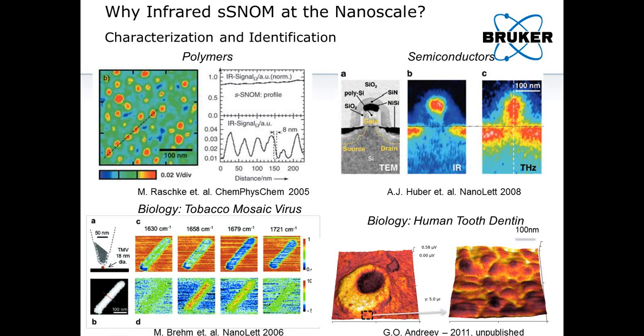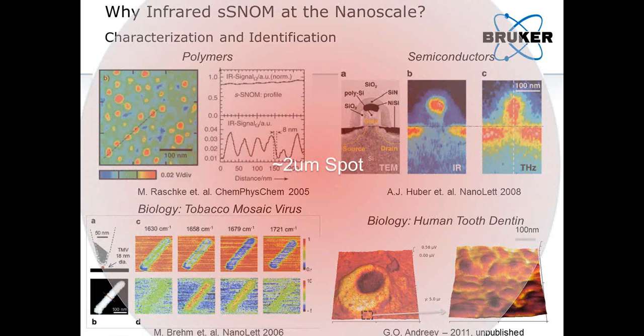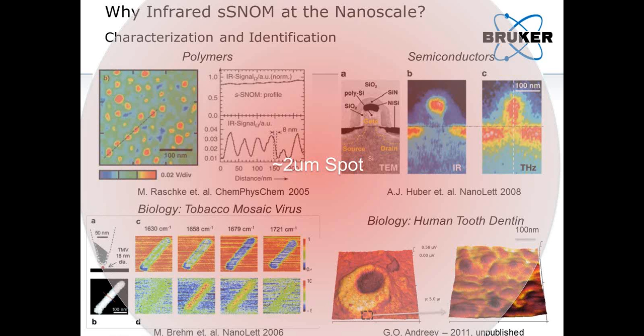What all of these images have in common is that they are much smaller than the typical spot size that you would achieve in an infrared microscope. So I put here a 2-micron spot, but actually the spot is going to depend on the wavelengths that you're using in your infrared microscope. So it can be as big as 10 microns.